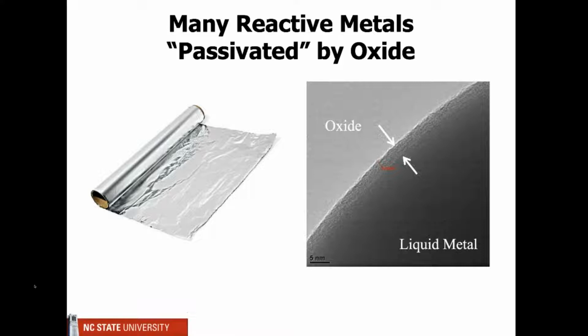Well, normally when you want to make electronics, you don't really want an oxide because they're insulators. But in our case, the oxide's very, very useful. So let me show you why. It allows us to shape the metal into shapes that would normally not be allowed by surface tension. This was work done by an undergrad, actually, and here you'll see we take droplets and dispense them from a nozzle, and they oxidize so fast that you can actually start stacking them like snowmen. Now remember, without the oxide, it would just form one big puddle, right? And so this whole principle is enabled by this oxide layer that's forming basically instantly and is very, very thin. So one thing you can do is stack droplets, and this is interesting because for the first time, at least I think the first time in history, you can print metals at room temperature with no additional processing.